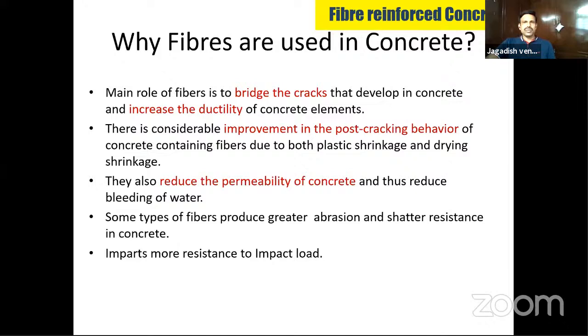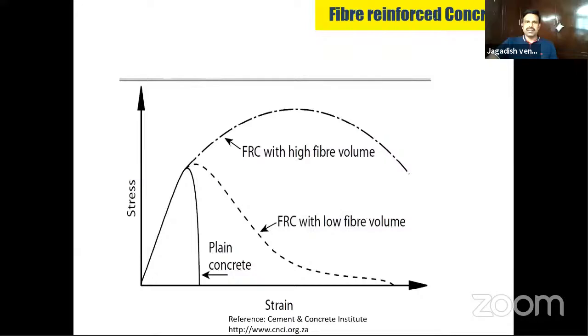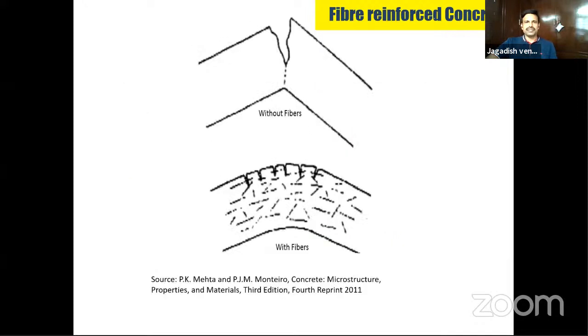Why do we use fibers? You need to bridge the cracks and also increase the ductility in the concrete elements. There is also a considerable improvement in the post-cracking behavior after using fibers. It will reduce the permeability, and some fibers will even increase the abrasion and shatter resistance. A typical graph shows the stress-strain curve for plain concrete, FRC with low fiber volume and FRC with high fiber volume. You can see the stress-strain behavior with fibers and without fibers. The fibers will arrest the cracking behavior of the concrete.